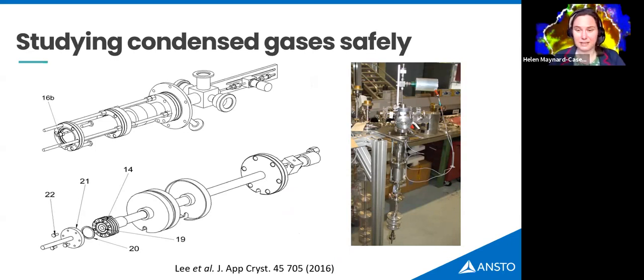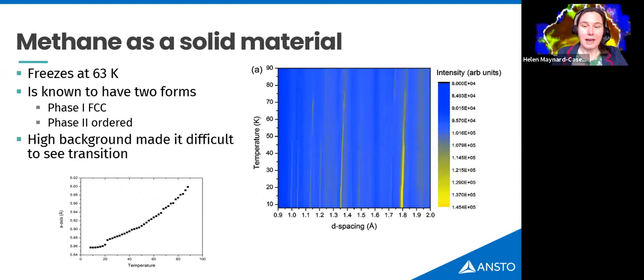And one of the reasons for that is because we've adapted these gas delivery sticks. So these go into our cryostat. They were originally designed to do gas dosing experiments for metal organic frameworks. So I've appropriated them to do some planetary science. And so it means that I can condense things like methane and nitrogen all the way down to around 5 Kelvin or so without too much trouble.